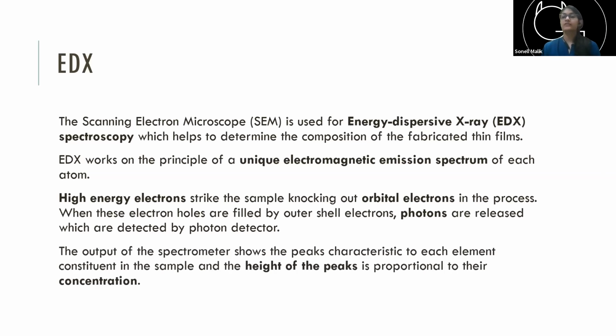At the end of the day, you bombard a lot of electrons, you collect a lot of photons emitted from your sample, and every element has a unique spectrum. So we know the exact energy of a photon that will come when an L shell electron is knocked out from, say, molybdenum, and it is replenished by the M shell electron in molybdenum itself. All of these things are noted, and there is a code written to determine that if this is the energy set of photons that you get, then it will be this particular material. And similarly, all other elements.